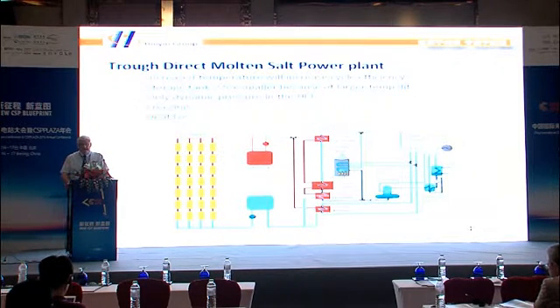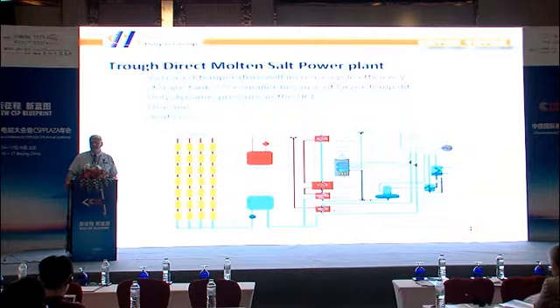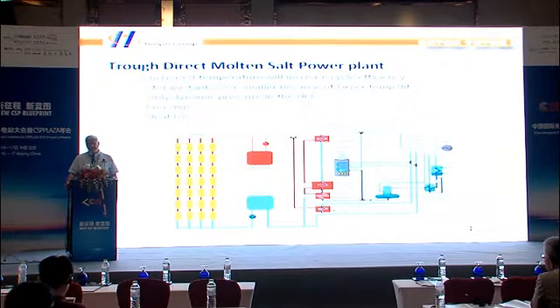So, direct molten salt in power plants, but why? Well, basically because we can run the salt directly through the receiver tubes. We can go to much higher temperatures instead of having a limitation caused by thermal oil to about 400 degrees. We can take it up to 550 degrees. And the biggest effect of this is that the storage will become much smaller. It will become about 2.5 times smaller.